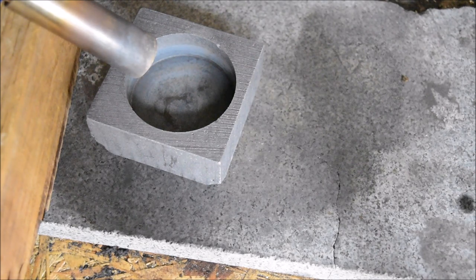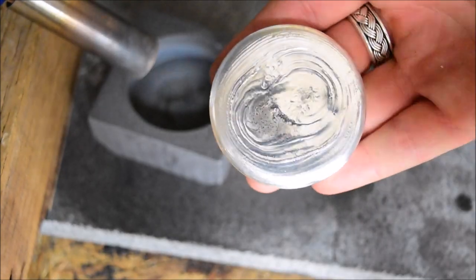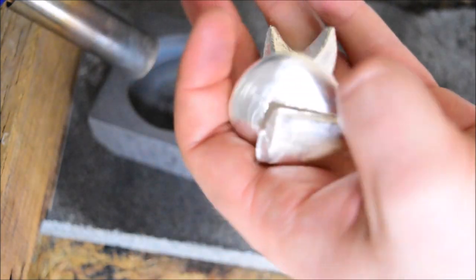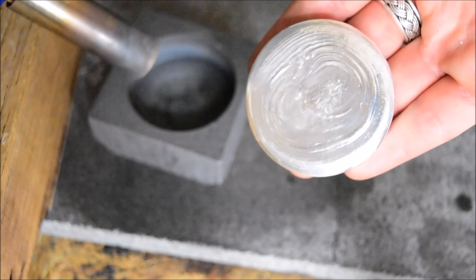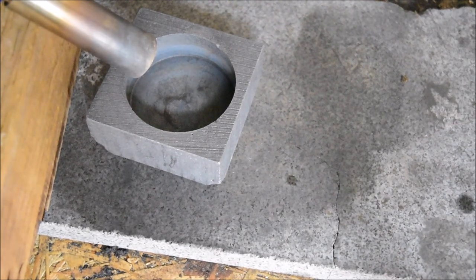Silver is coming up to temperature for the second round, but while we were waiting I've gone and cleaned the first round. It's got some really cool ripple lines, but we did see all that kind of pollution on top when it first came out. I think that's to do with what I used to pour it with — I was melting down old pieces where things hadn't gone quite so well, hammered down to fit back in the crucible. I've noticed that when I use stuff like that it doesn't pour quite as smoothly as silver shot. So I've exclusively used shot in the next crucible — hopefully when we pour this one we'll have a really nice result.